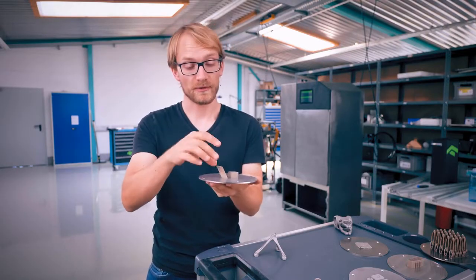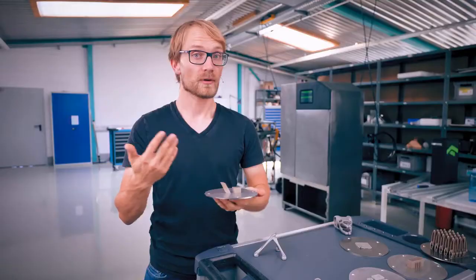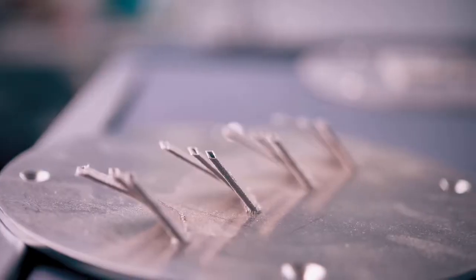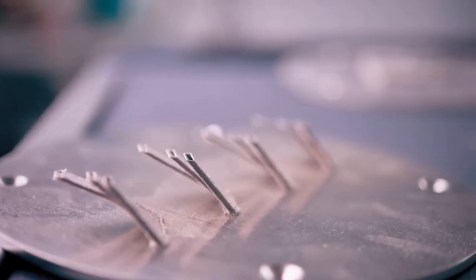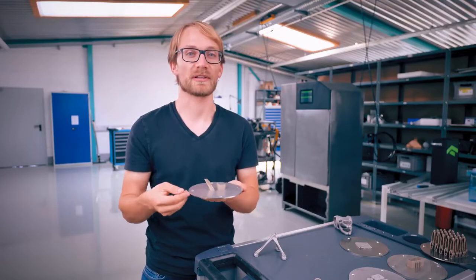But there's also less material there for cooling. If the heat from the melting process has nowhere to escape to quickly enough, areas can actually overheat and degrade the print quality. You can push some metals further than others here, but generally a 45-degree angle can be considered safe, this is 30 degrees.